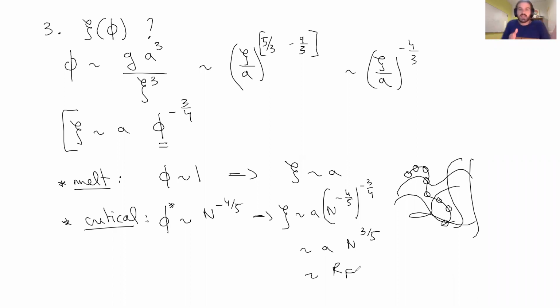So now at the opposite limit, when you start to really increase the size of the blobs, meaning there are less and less monomers, at some point, at the critical concentration between dilute and semi-dilute regimes, a blob is the full chain itself. So it's a very interesting mapping, because now it says that, in fact, a polymer solution can be viewed as a melt of blob chains.